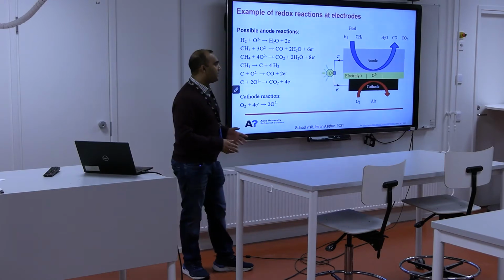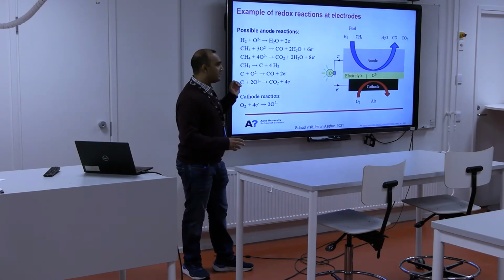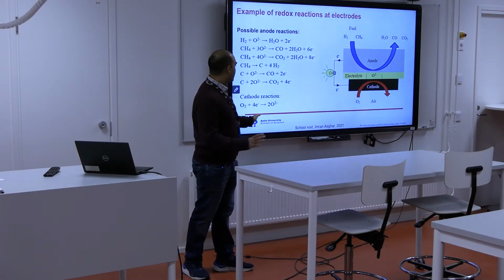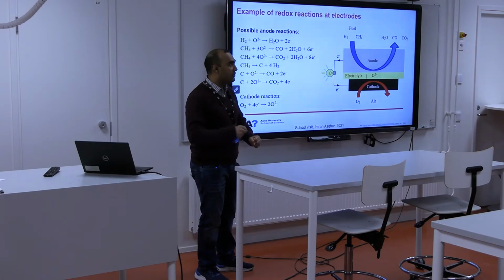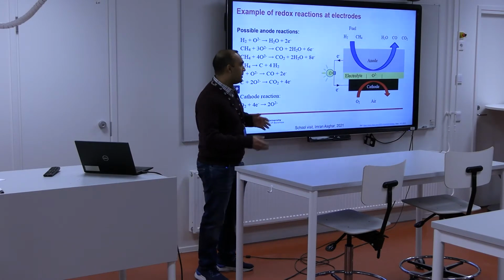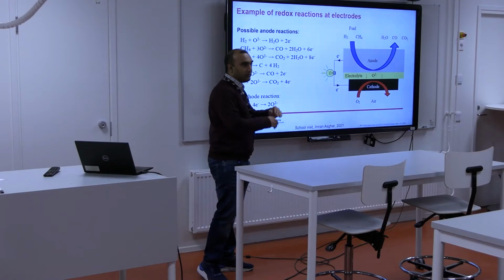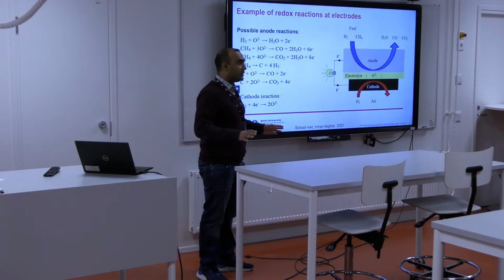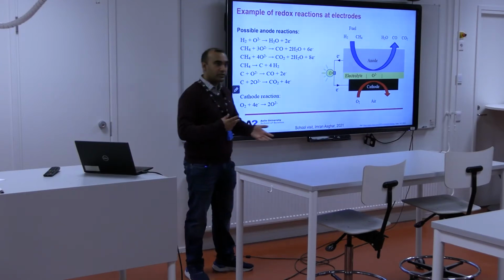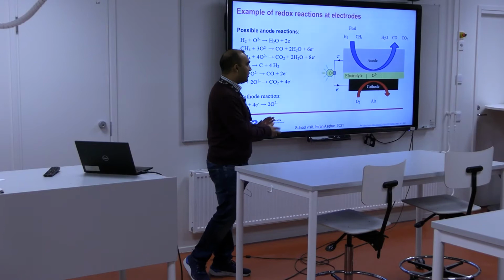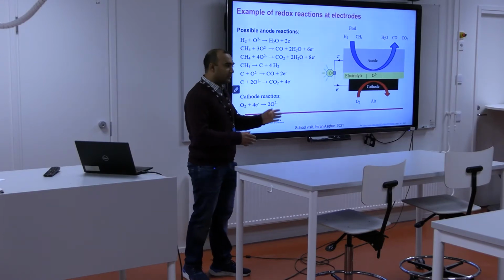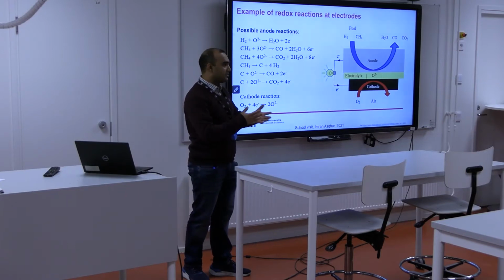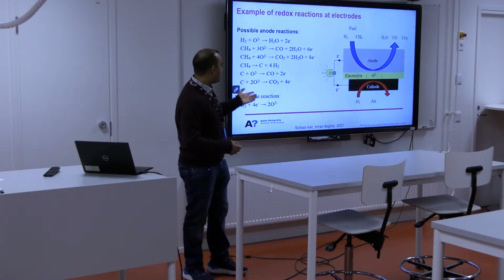This is a typical problem in solid oxide fuel cells: there's lots of carbon on the anode side, and it just blocks all the sites for reaction. So that's one challenge, and we are developing materials that can block this carbon formation, or carbon formation will happen, but we try to avoid agglomeration of this carbon at the anode. So this is a very hot topic of research. How can we avoid carbon formation on electrodes? Because when carbon formation happens, it covers the electrodes and their interfaces with the gases, so there's less surface area, and surface area is very important for electrodes.